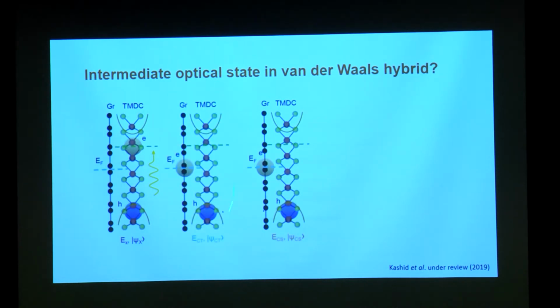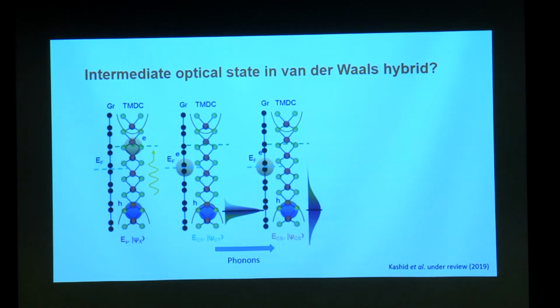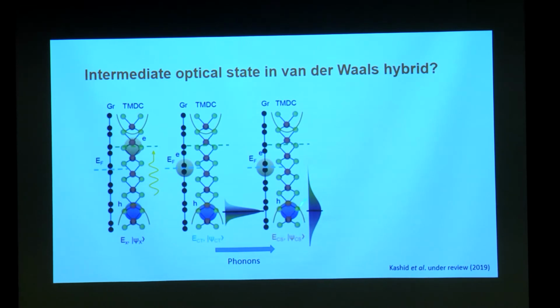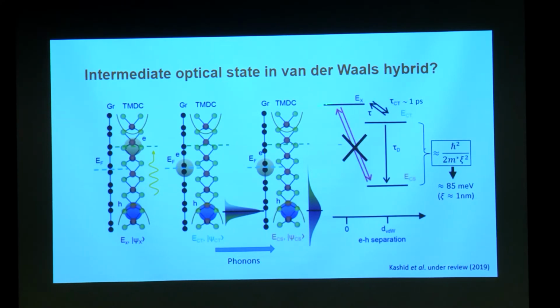An intermediate state is what you call a charge transfer state, and the difference between the intermediate state and the final state is the nature of the wave function of the hole that's there. So this is a strongly localized hole, and this is a delocalized hole, which has come through the emission of interface phonons. So the overall energy diagram will be that this is the highest energy state, which is the electron over here, and we have the lowest energy state, which is, of course, where the photon is absent. I'm discarding that out at this point. But this is the charge separated state, which is essentially the free electron in graphene layer and a delocalized hole in the transition metal dichalcogenide layer.